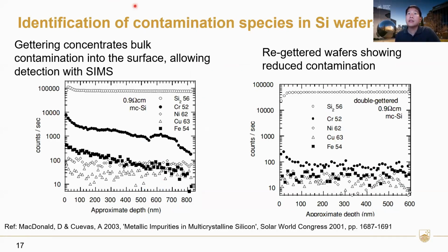Another one, a bit of an older reference mainly focusing on multicrystalline silicon, shows that SIMS can also be used to identify contamination species in silicon wafers. Typically this is quite difficult because the concentration of impurities in the bulk is too low, below the detection limit of SIMS, because it doesn't take a lot of metal impurities to severely affect the lifetime of a sample. But if we do gettering, in this case a phosphorus diffusion, we can concentrate most of the iron and metal impurities into the front surface, allowing them to be measured on SIMS.